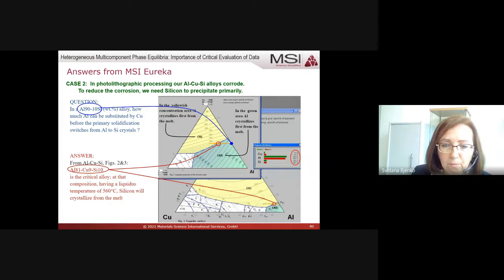This is the initial composition which they had, and so they want to add copper to this. So we move along the copper concentration, and as soon as we are on the border between the yellow and the green field, the primary crystallization phase is already silicon. Then we determine this composition and give the answer: once you reach this composition, you can add a bit more of copper, but already starting with 9% of copper, you will have silicon crystallizing primarily from the melt.